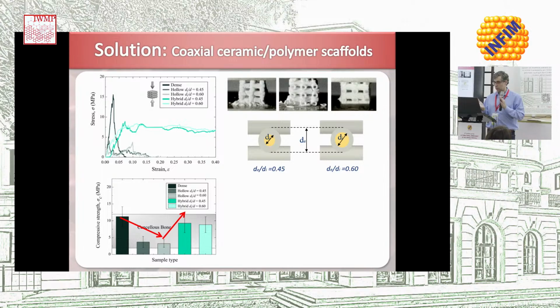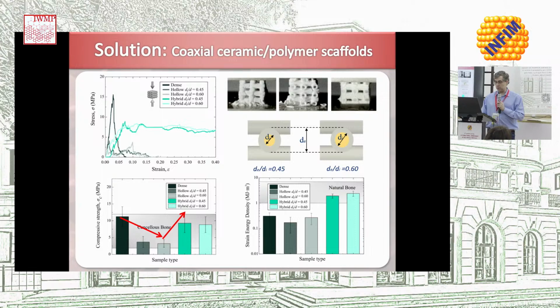So that's good in compressive strength. There was not much, but the main important feature that we wanted to get was not strength. We weren't expecting an improvement, of course, in strength, rather what I showed, a reduction of it. But the good thing is that we did get what we wanted. This is an increase in the toughness of the structure.